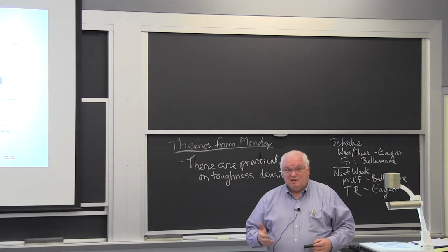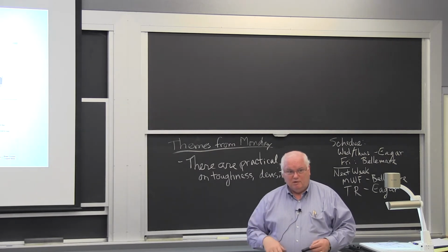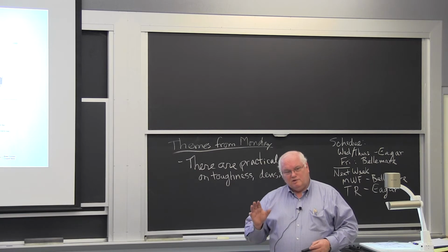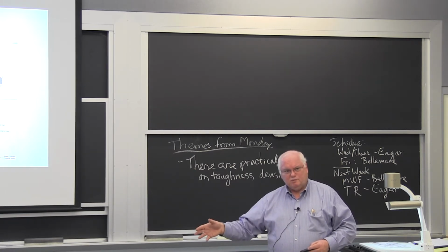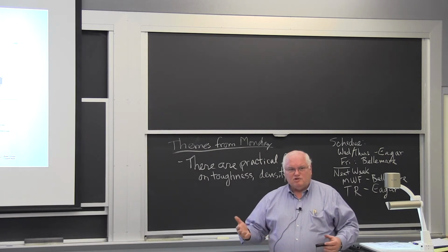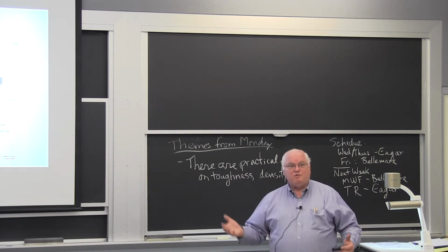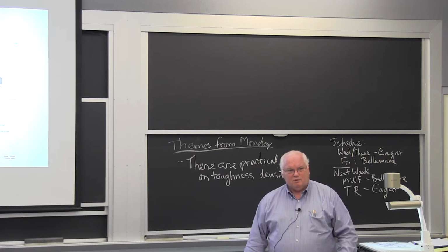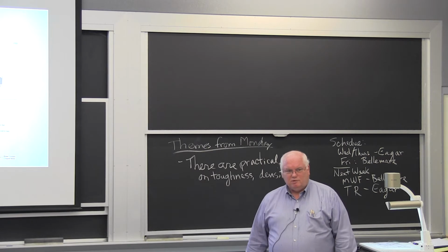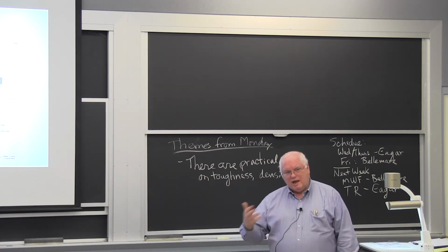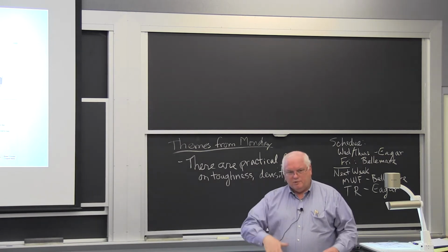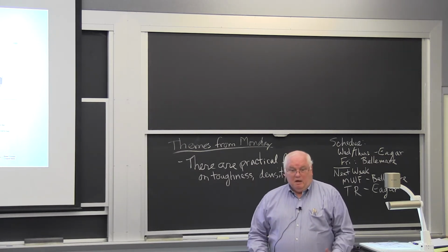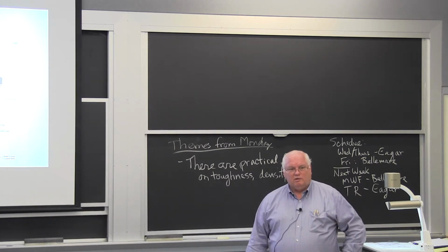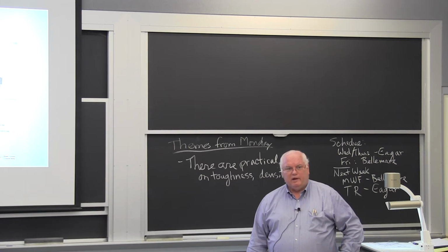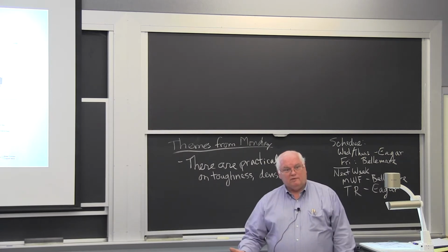But you could end up with 300 tons of the wrong chemistry steel, which you got to downgrade or even remelt. Well, John Chipman came along, and using the principles of physical chemistry, he was a physical chemist from Georgia Tech. And he came up here and he applied those same principles to high temperature physical chemistry, not aqueous chemistry, which is what the chemists were doing in water baths. He basically applied the same principles to high temperature glass slag baths and steel, and figured out how the elements partition between the slag phase and the metal phase. And so now we can hit those chemistries right on. You get one bad chemistry out of 100 heats today, whereas in the old days you probably got 10, 20, 30% bad heats. So that's one of the things about productivity.